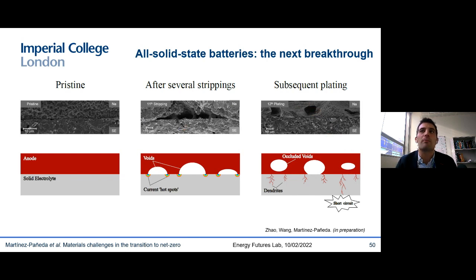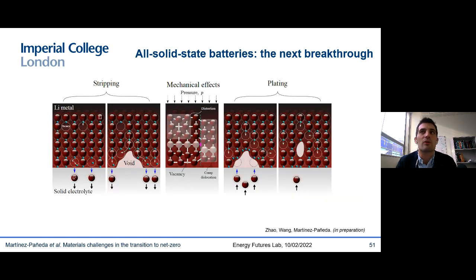And understanding this voiding process is critical because when these voids form, they lead to local current hotspots, so to say. They're called current hotspots, basically near their edges. And these hotspots are small regions of high local current, and these current hotspots are basically acting as precursors for the nucleation of dendrites, which grow to cause cell death. So we have developed a model that captures the main physical phenomena and that can predict for the first time how voids nucleate and evolve and how this leads to hotspot formation.